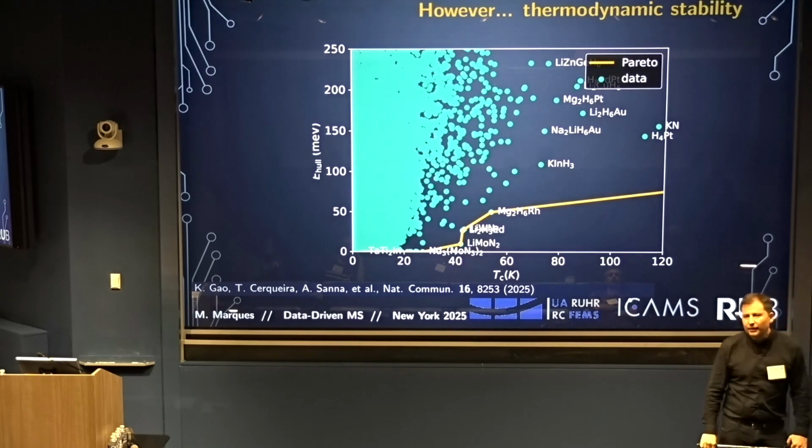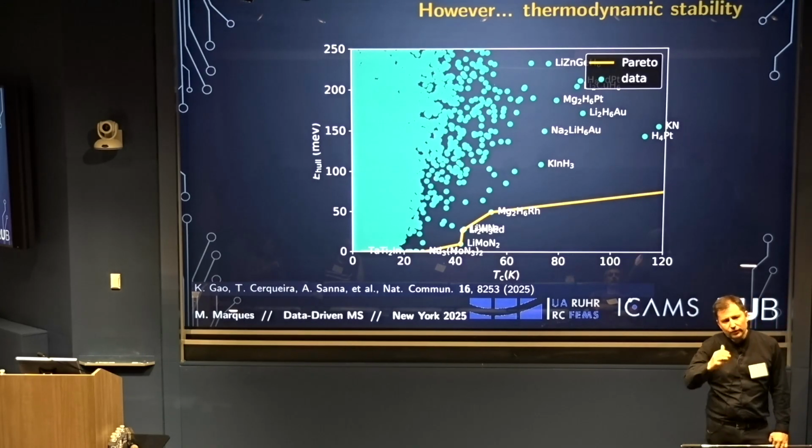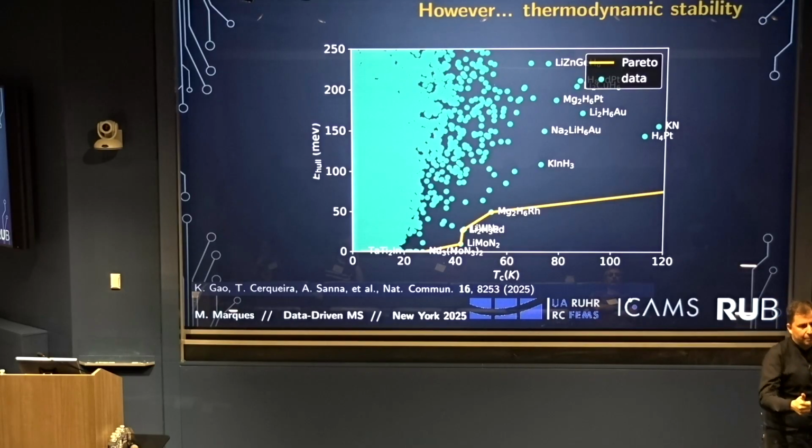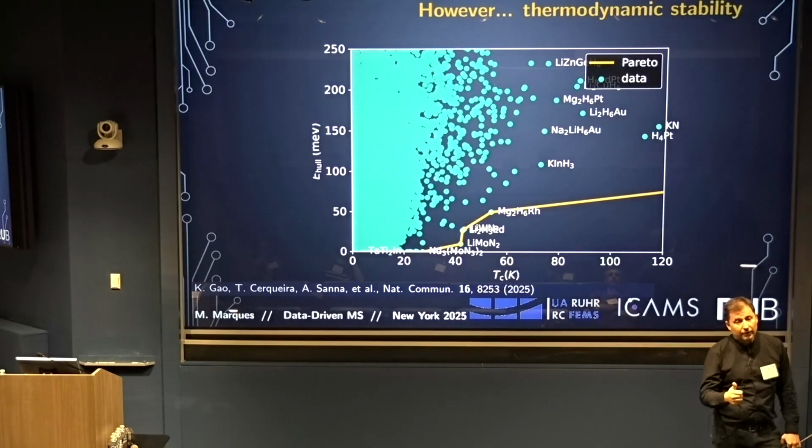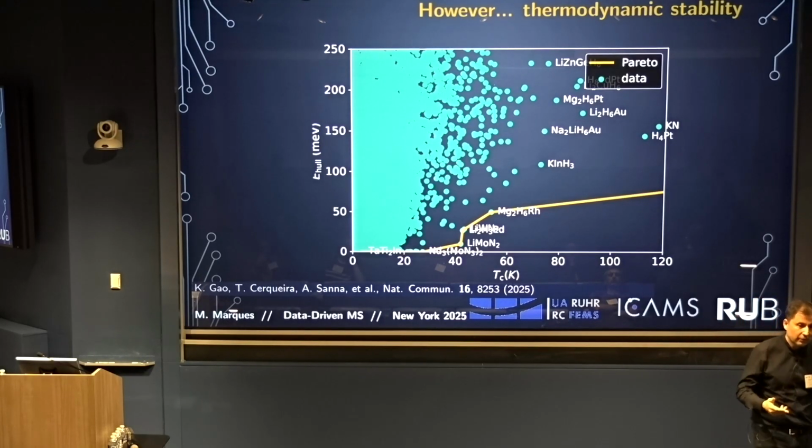So there are several parts. First of all, the materials have to be stabilized by pressure enough, at low pressures, and that's what you would like, because I don't believe you can quench a hydride from 100 GPa to 0. Hydrogens are too mobile.